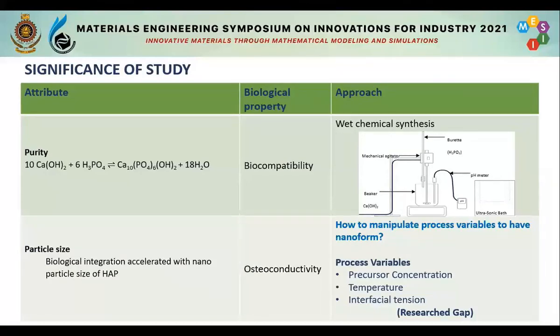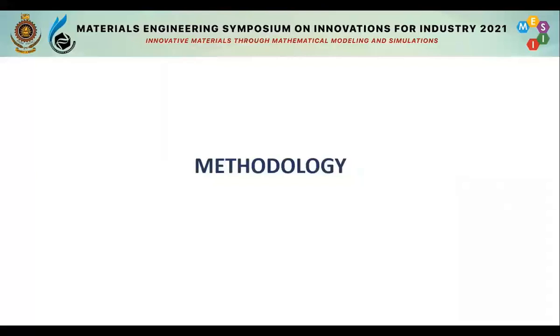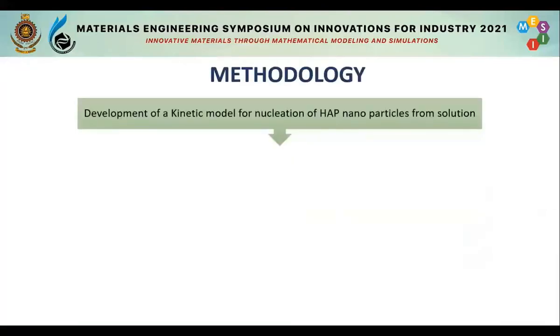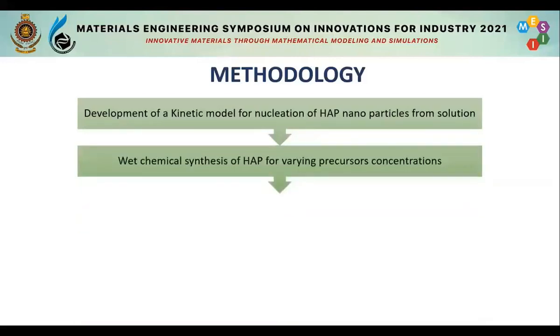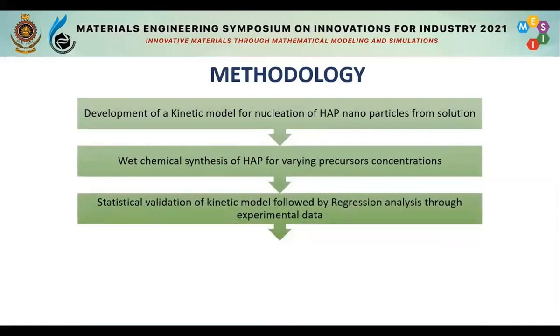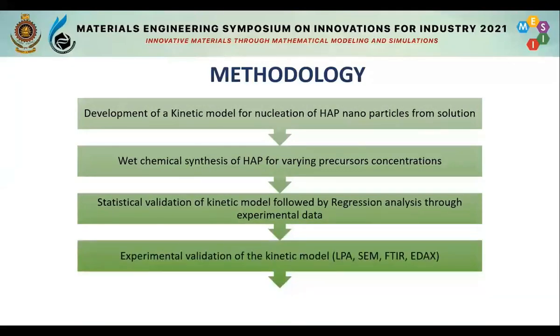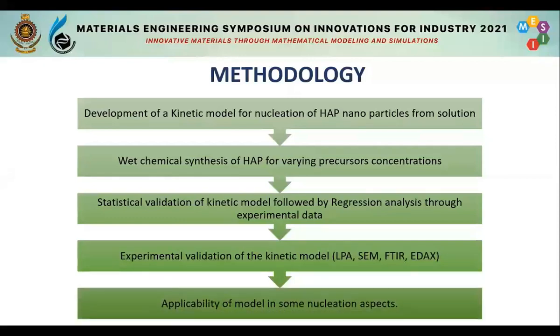Now, basically, the significance of this study is the purity achieved from biocompatibility. It is done with the wet chemical synthesis method. Then the particle size derived from osteoconductivity. Actually, it is the research gap because some process parameters which are sensitive to particle size needed to be understood based on some mathematical relations. In the methodology section, first thing was to develop a kinetic model based on classical nucleation theory. Then we designed our experimental routine to the wet chemical synthesis method for the formation. Then we statistically validated the kinetic model built. Then we experimentally validated through some analytical instrumentation. Finally, we applied the model built in some nucleation aspects.